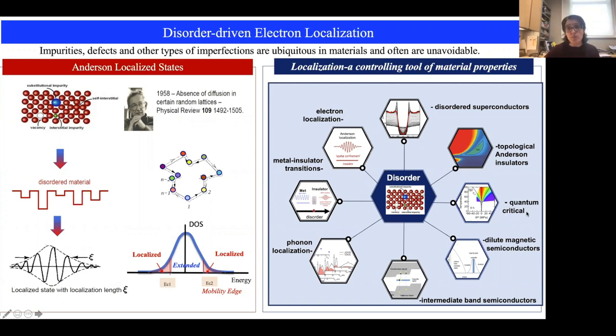Of course, disorder is very important for semiconducting materials, in particular for intermediate band semiconductors, where localization of electrons in this intermediate phase can control the photoemission effect and photoconducting effect. So this is important for developing more efficient solar cells. And of course, electron localization due to disorder is another mechanism to localize electrons in the system. And I just want to mention that this is not only for electronic systems, disorder-driven localization is present in any disordered medium, for example, phonon localization.